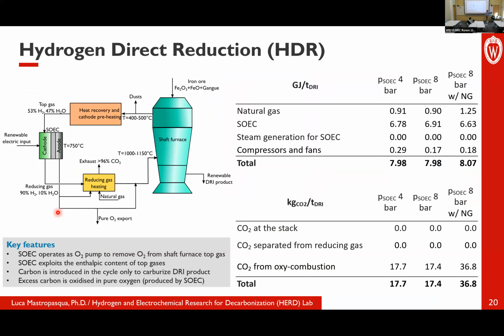So the process we proposed uses an SOEC that takes the top gas or exhaust gas of a conventional DRI furnace. It preheats that gas and it feeds it to the cathode of the SOEC. So remember, the cathode is where you feed the steam in a conventional SOEC. So the top gas stream is relatively rich in steam, and there is some hydrogen in that composition. So the SOEC converts the steam to produce a hydrogen-rich stream.